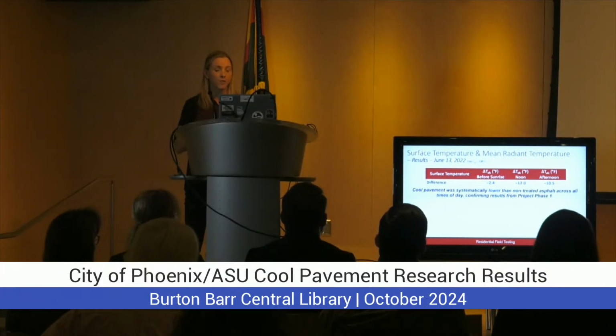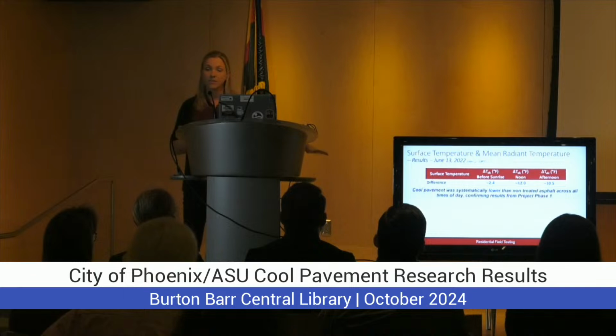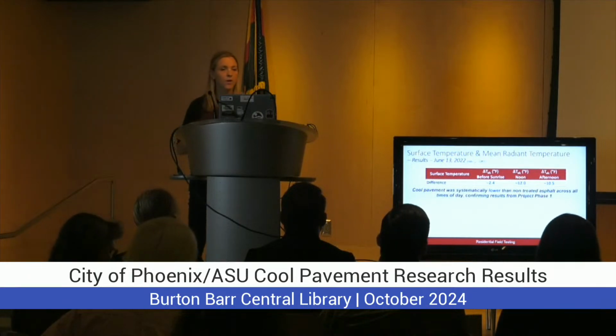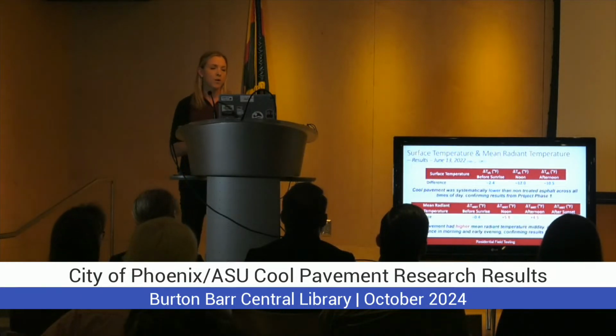So very similar results for surface temperature. We saw reductions throughout the day, especially at noon and afternoon, of up to 12 degrees Fahrenheit in the surface temperature. That's touching the surface. Your dogs are happy about that one. Very similar to phase 1 results.